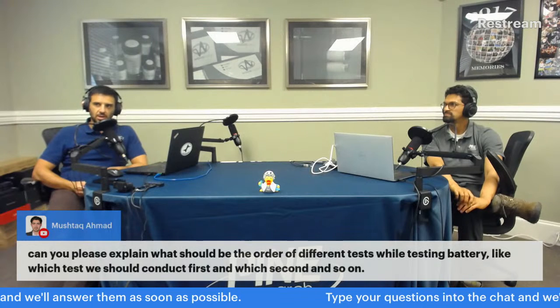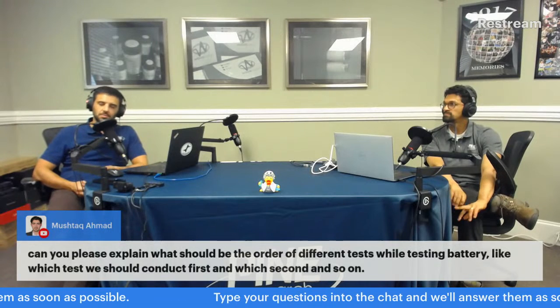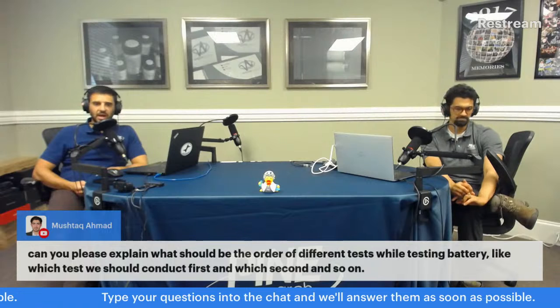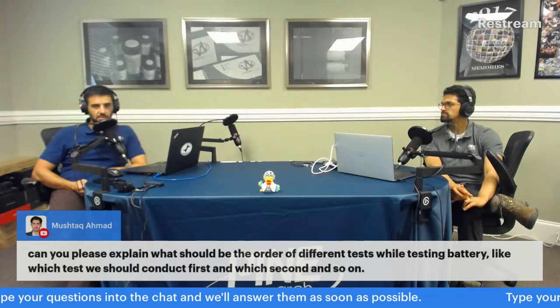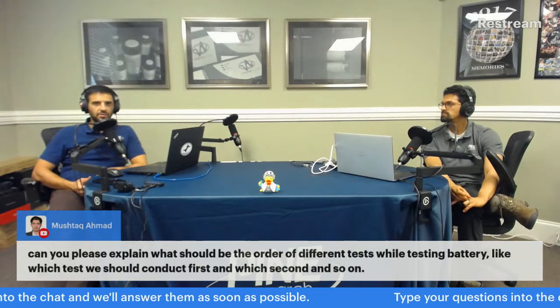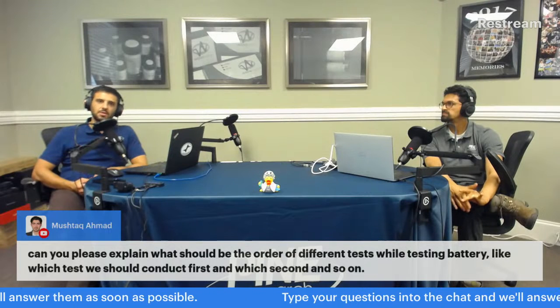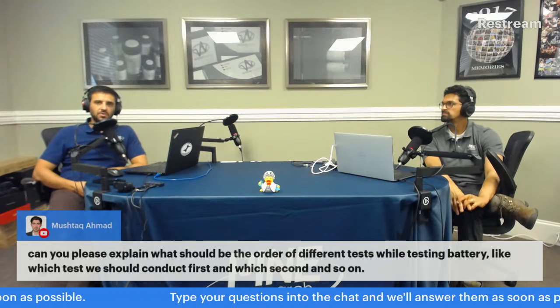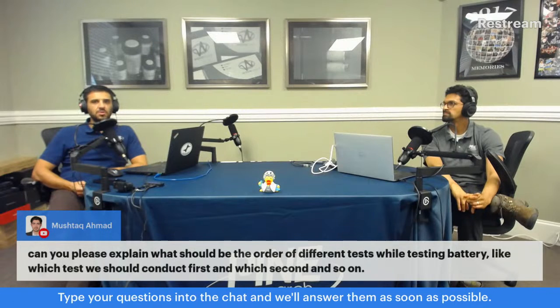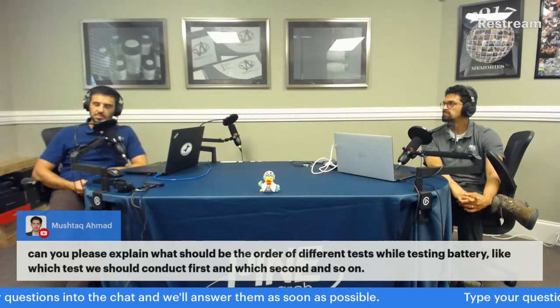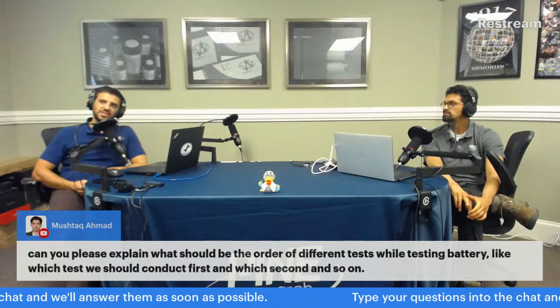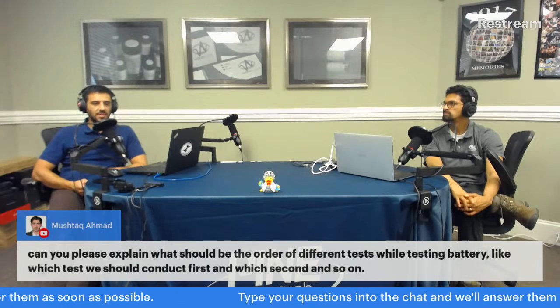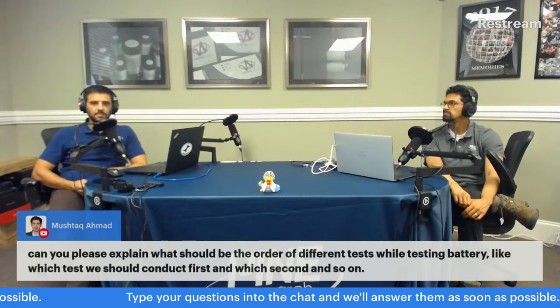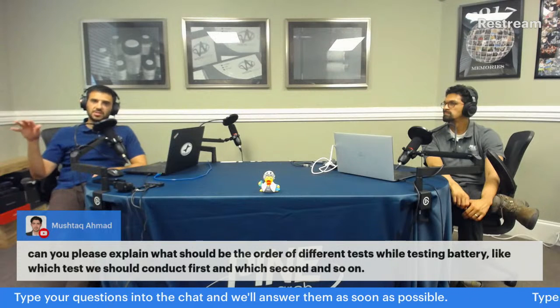So you take your battery, if it's fully discharged, or whatever state it's in, and you apply a constant current, CC, until the voltage reaches some upper limit. And then you do a constant voltage at that upper limit until the current drops below some certain value. That's the CCCV charging portion.